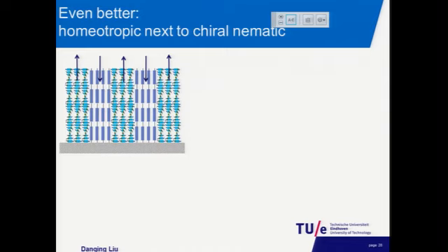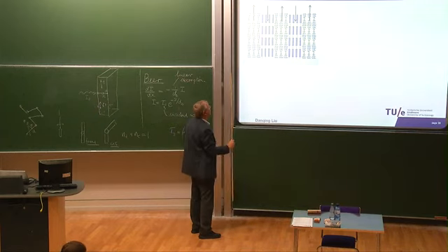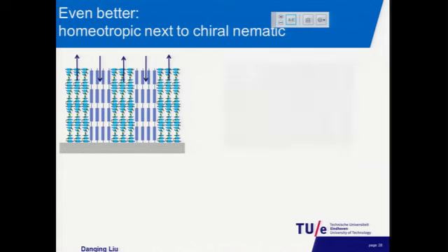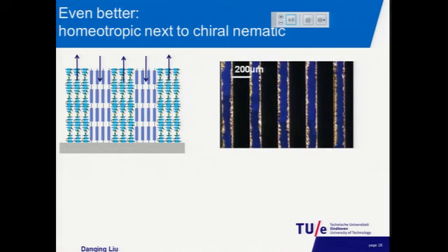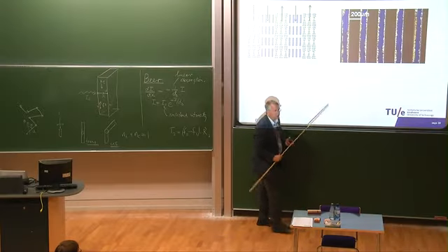So actually she came up with another idea, and this is the following. She made elements of this chiral nematic next to homeotropic elements. And in that case, you can more or less envisage that they are helping each other. This one wants to shrink, according to the models that we showed this morning from Mark. This one wants to expand. So what you can hope for is that you see a larger protrusion. This is the film that she made. So black is homeotropic, apparently isotropic. Blue is the chiral nematic one. And what you see is also that we have transitions between one state or the other.